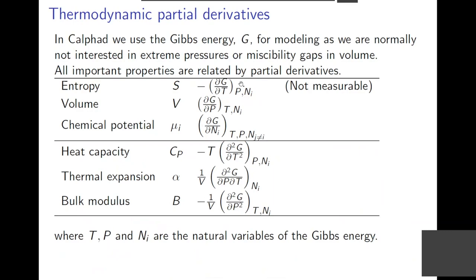Of course, this is all controlled by partial derivatives. So when you control the pressure and the amount of the system, the negative of the Gibbs energy with respect to temperature is the entropy. The volume is the pressure derivative. Chemical potential is the derivative with respect to the amounts. And it's always important to check what conditions you have kept fixed, because heat capacity will not be the same if you can control the activity of a component. So those things are basically important for your understanding.